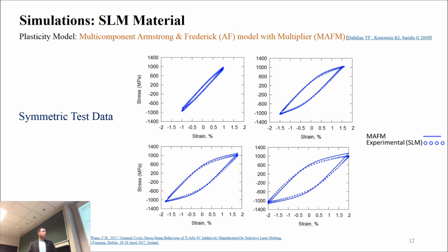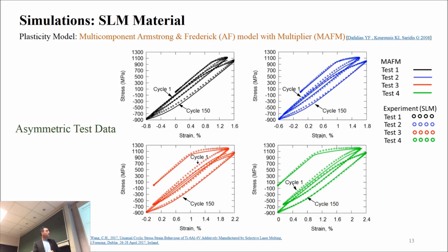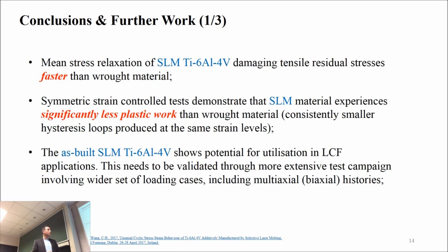Some complementary work trying to simulate these results. So we have been using some models, trying to identify the best possible model which is available in the literature to simulate these results. So we used one of the models which have been used in the past for other metals, both for simulating symmetric test data, but also the asymmetric test data. And we found that there is a very good agreement in that regard. So this is helpful for simulation purposes without having someone to reinvent or to modify an existing model. So the SLM material seems accommodating in that regard.